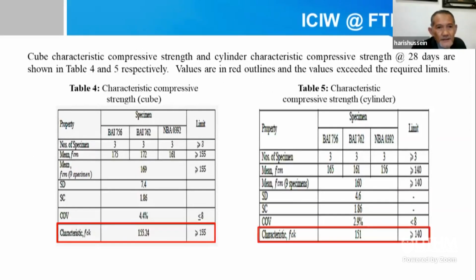Table 4 shows the characteristic compressive strength, carried out on several cube samples, and the value achieved was 155.24, which exceeded the value of 155. For characteristic compressive strength for cylinder, it is 151 against 140, which exceeds the limit required for the concrete grade.